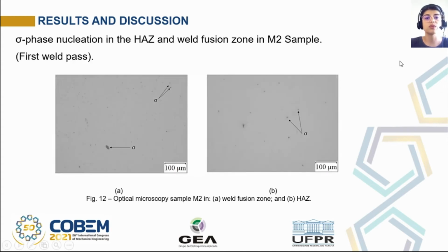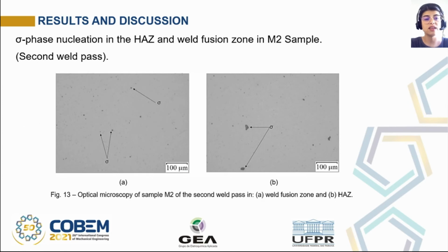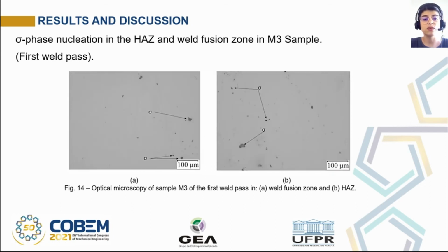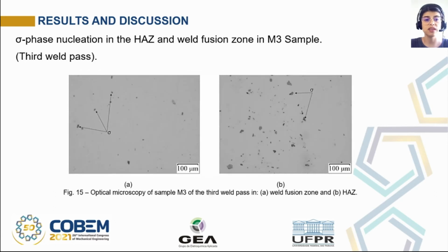Figure 12 shows the optical microscope of M2 and the first weld pass, and letter A shows the weld fusion zone, and letter B shows the HAZ. Figure 13 shows the optical microscope of sample M2 and the second weld pass, and letter A shows the weld fusion zone, and letter B the HAZ. Figure 14 shows the microscopy of M3 and the first weld pass. Letter A shows the weld fusion zone, and letter B shows the HAZ. Figure 15 shows the microscopy of M3 in the third weld pass. Like the other microscopies, letter A is the weld fusion zone and letter B is the HAZ. This result is similar to the others because the HAZ presents more sigma phase than the weld fusion zone.